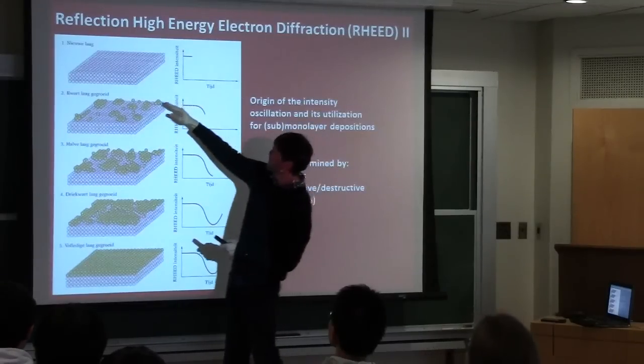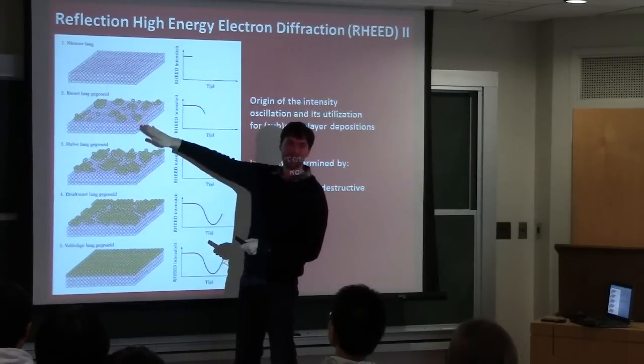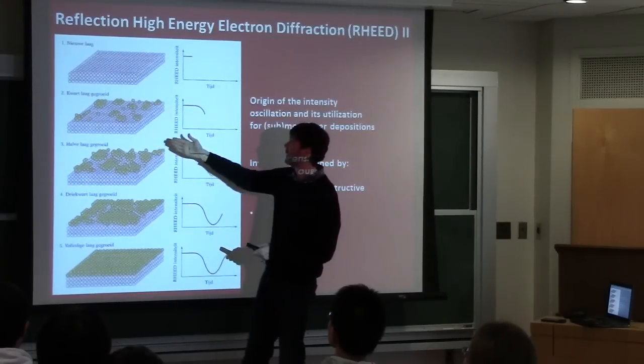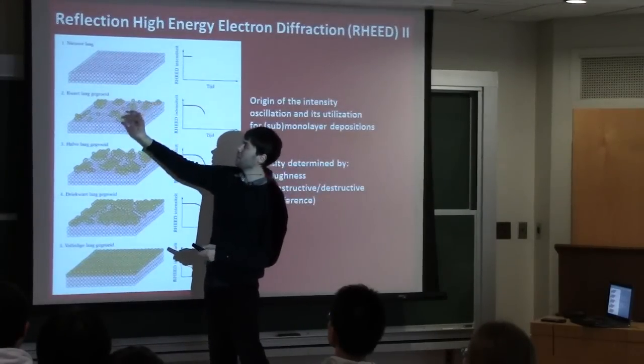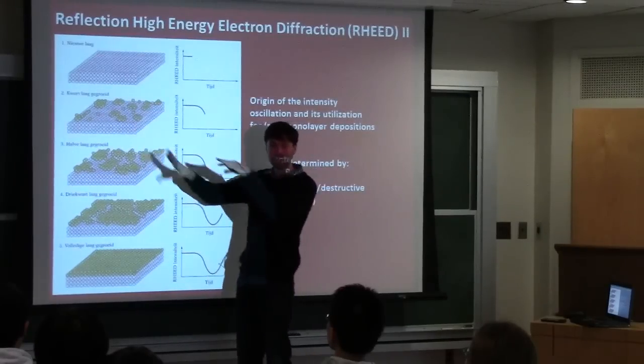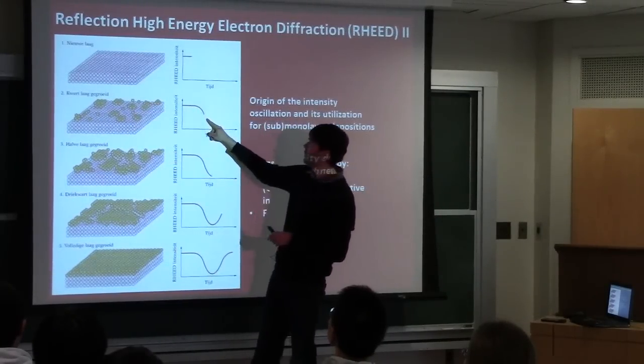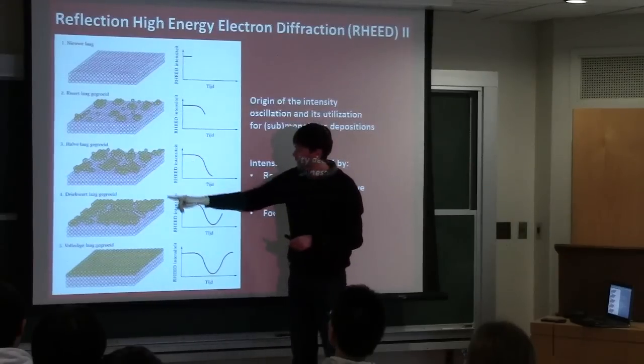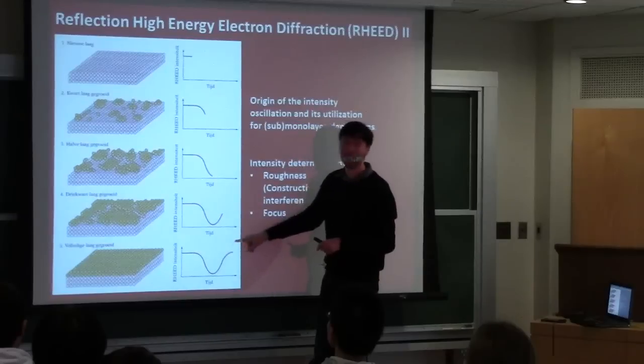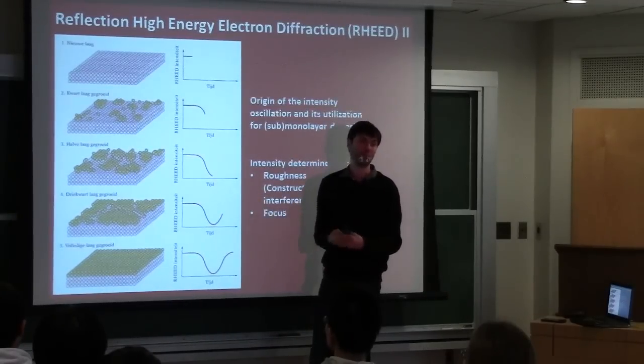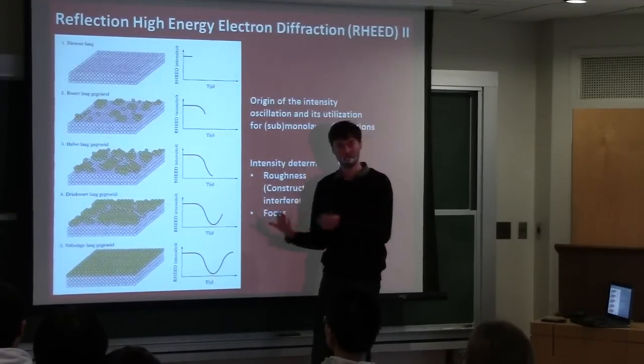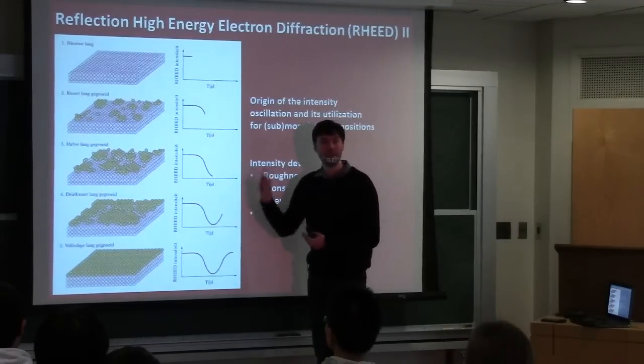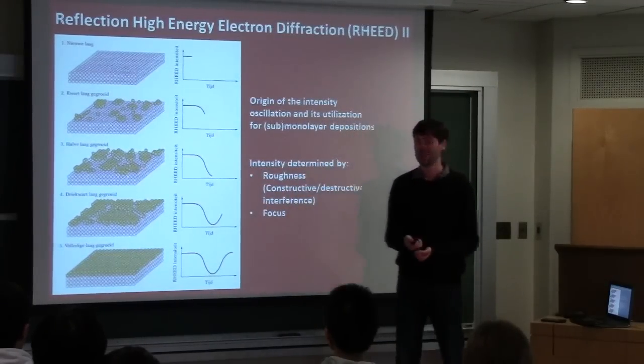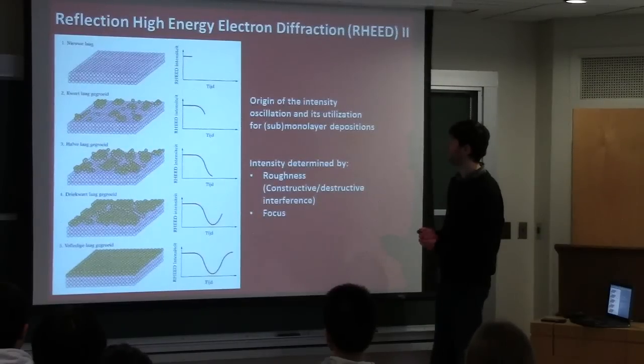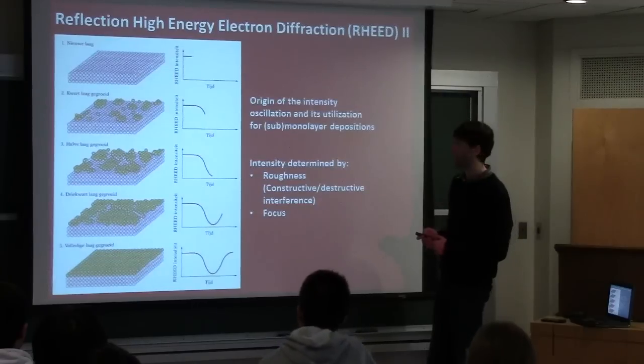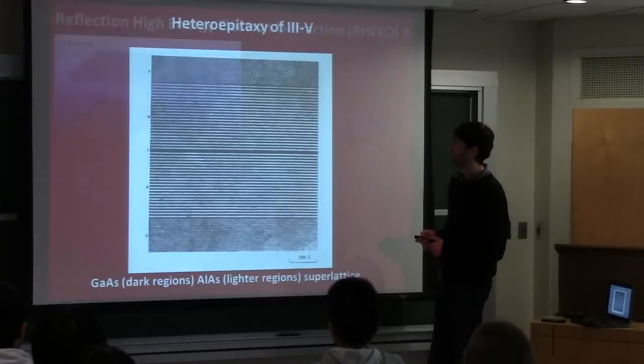Three quarters. Yeah. So they start with a perfect finished layer, and then you start growing the next layer, and they start getting these little clusters of atoms as they diffuse around the surface, and the intensity of the read signal goes down, and then finally when they reach the next perfect layer, the intensity is back up. So you go from destructive to constructive interference back and forth, and so they can just count as they grow. So they know what's going on in situ. This is very powerful, that they can monitor this monolayer by monolayer growth.